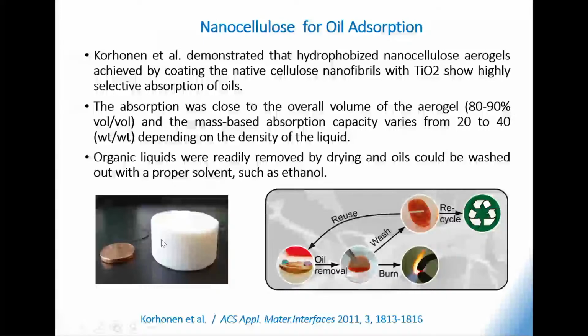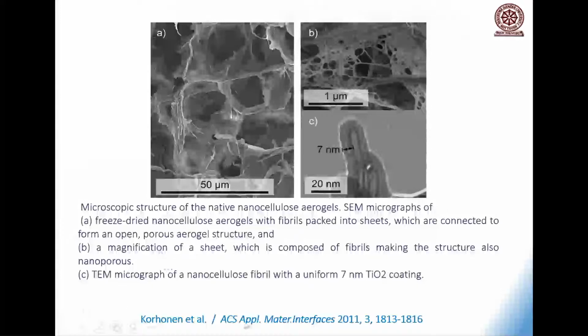Look at the aerogel made by the Finland group. Nanocellulose and water, you go for freeze drying, you can make aerogel. You can do it in your laboratory, manufacturing aerogel. Some 2% of nanocellulose in water, go for a freeze drying process, you can make beautiful aerogel. The interesting part the Finland group did is, they made the surface of nanocellulose hydrophobic by giving a coating of TiO2. Look at the TiO2 coating on the surface of nanocellulose.